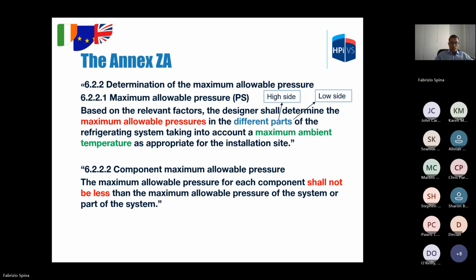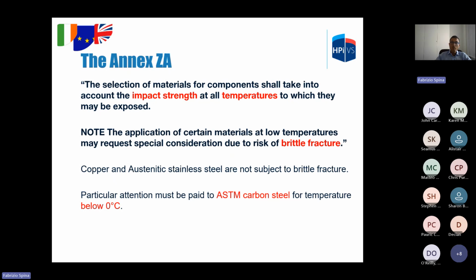The component maximum allowable pressure shall not be less than the maximum allowable pressure of the system or part of the system. It is the same as what we saw before about the integration of the system within the global conformity assessment. The selection of material for components shall take into account the impact strength at all temperatures to which they may be exposed. The application of certain materials at low temperatures may require special consideration due to the risk of brittle fracture. This is a very important point.